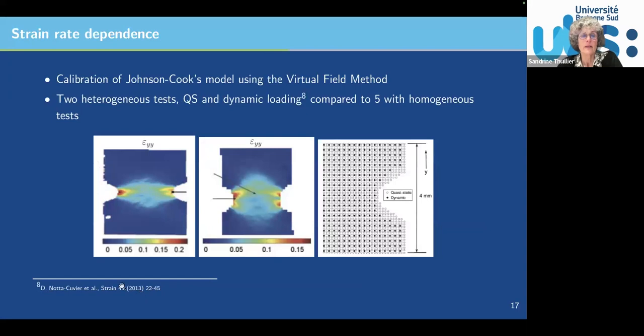Now, from the literature, people have also used this approach to calibrate the Johnson-Cook model. I guess you know Johnson-Cook will give you a dependence, in this case not on temperature, but mainly on the strain rate sensitivity. And so to calibrate, you will need several tests at different strain rates. And in this case, you've got here the quasi-static test, and this one is the dynamic test. They considered two heterogeneous tests, one in quasi-static condition, one in dynamic loading. And they succeeded in calibrating the Johnson-Cook model with only these two tests compared to 5 with homogeneous tests.